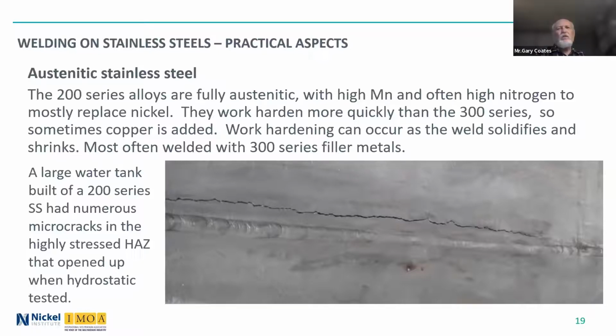They work harden more quickly than the 300 series. Sometimes they will add copper to them because that lowers the work hardening rate. Work hardening of the material can occur as the weld solidifies and shrinks, so it's pulling the material away. These materials are often welded with the 300 series filler metals.